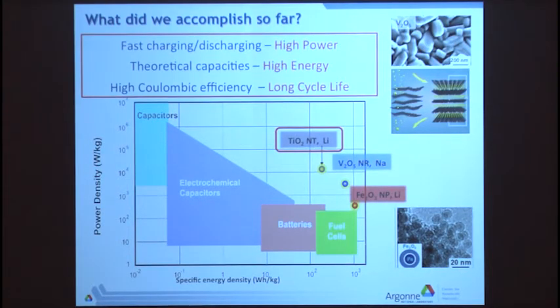Now, of course, the other thing at the nanoscale is everything's very close together. It's very small distances. And another thing I should have said about this battery is that it's very efficient. That's because in a battery, you generate an electron and a hole. A hole is a positively charged electron. They travel in opposite directions, and that is eventually going to give you the voltage across the battery, which is what we're going to use. If that electron and hole have to travel long distances, they knock into atoms and get scattered and stop moving. If you make the distances very small, there aren't very many atoms they could hit on the way. So it becomes much more efficient, and that's another very good reason for going to nano.